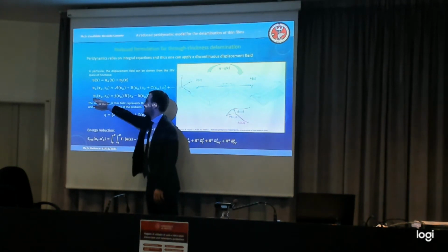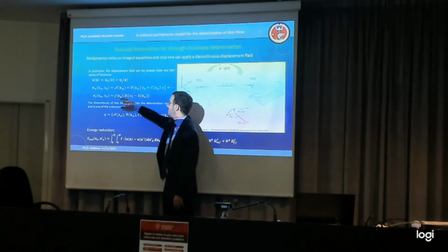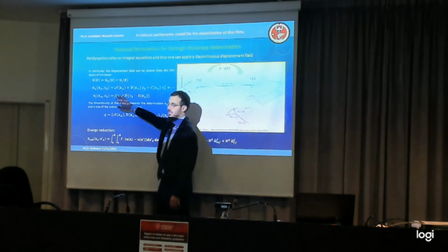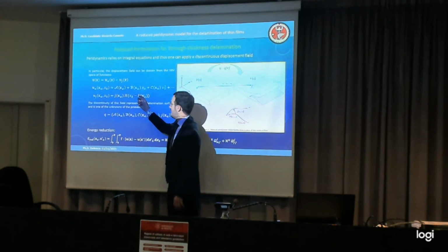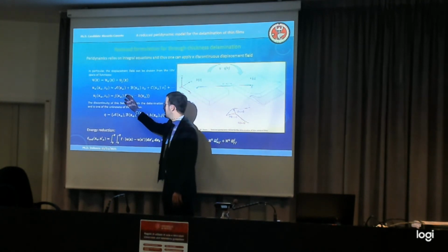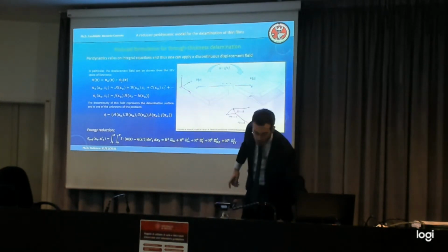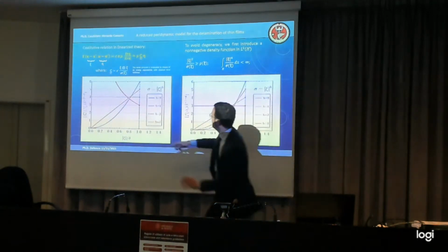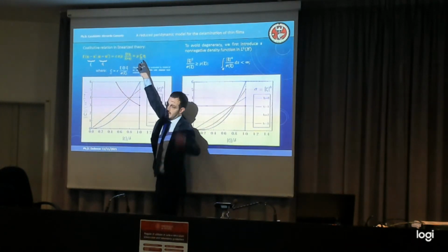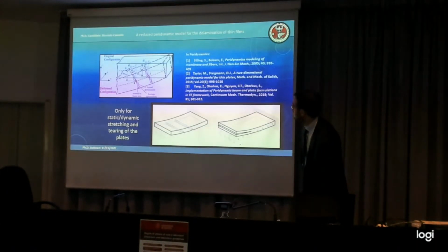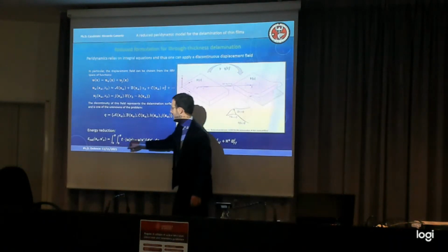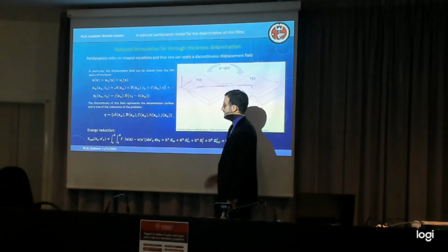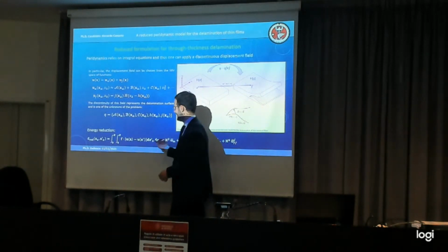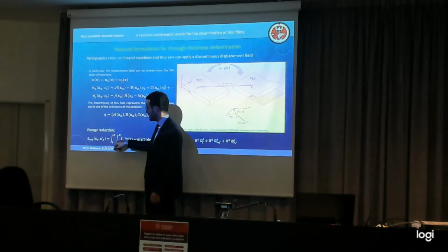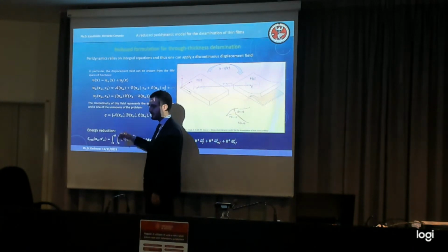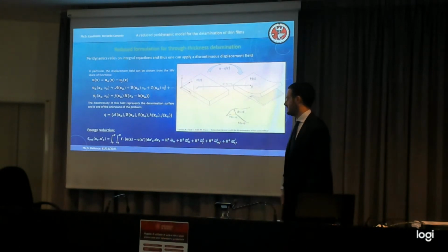We started from one vectorial unknown field, and we have only two here on this side. So we pass from one to two, and in this way, since the thickness variable is explicit, you can grab them and put them here. This is the relative displacement. So you take the displacement that you have, and you integrate. And then you extract all the terms at different orders. Actually, here I just realized there's a mistake. This is something that I copied from a previous version. The integration is from minus h divided by 2 to h divided by 2, because the reduction plane is in the middle. There's a mistake.